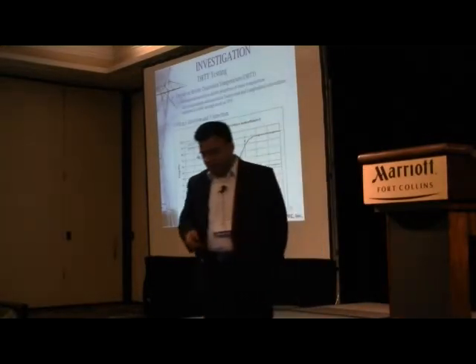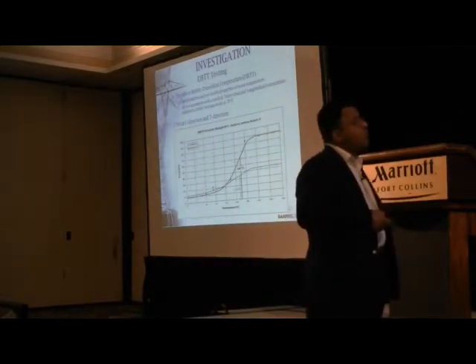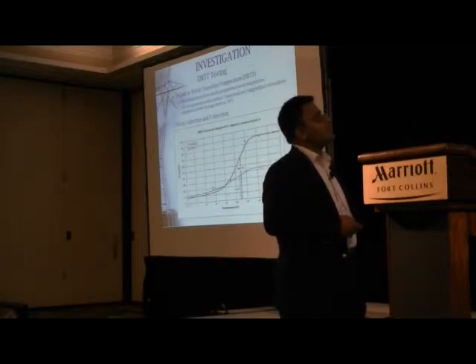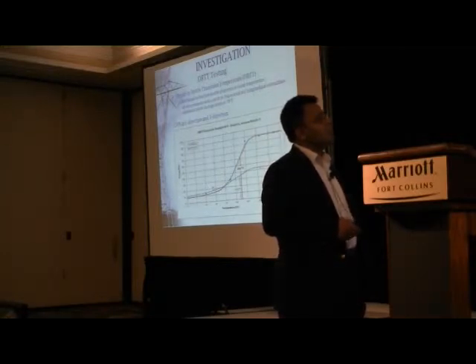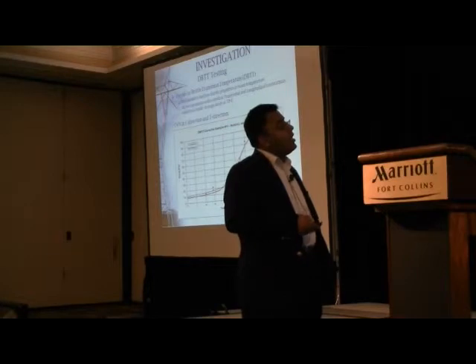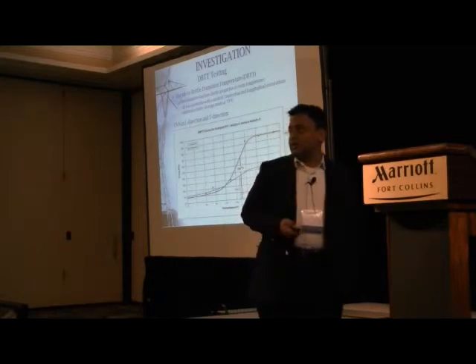So there was a lot of lab testing done. This particular one we're trying to find out is that we did a Charpy test in the longitudinal direction and the transverse direction and compared the performance. If you see here, this is the ductile to brittle transition temperature. The steel member had low ductility at room temperature, as you can see here. All the specimens with the notch, either in the L notch or T notch direction, show a brittle cleavage mode. This is most common if you don't have Charpy requirements, you'll see that kind of thing. One thing you notice here is that you have a better performance with the red one in the T notch, but normally we say the longitudinal direction notch that we have already.